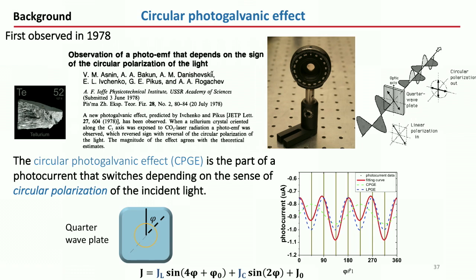Okay. So this effect was discovered in Russia, like many things, in the 1970s on tellurium. And what happened, so this is the experiment. You measure photocurrent without applying any bias as a function of the polarization. So you start with linear polarization. At this point, you have left circularly polarized light. Then at this point, you have right circularly polarized light.